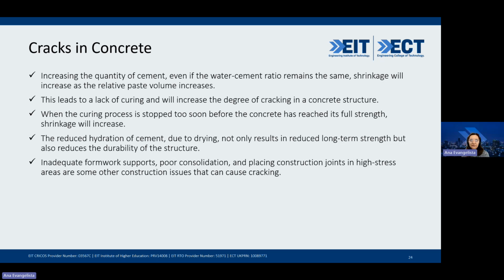So cracks in concrete, we mentioned at the very beginning concrete as a composite material. More and more we know that when you have Portland cement plus water, it's a chemical reaction, an exothermic reaction. That's why when you replace part of Portland cement by fly ash, for example, you can have mitigation and you can observe some reduction in the heat of hydration. All this can reduce the probability of cracks in your concrete. Also here, during the hydration, when you think about long-term characteristics in terms of strength and durability of concrete, everything that you pay attention to at the very beginning will ensure long service life of your structural element.